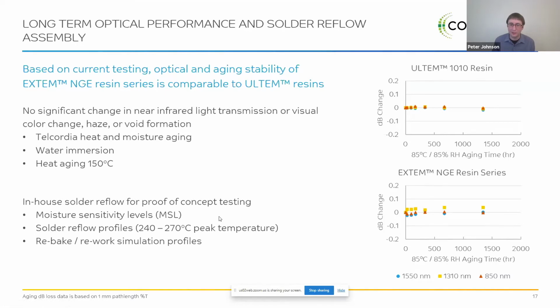of concept testing. So when we say we have done 3 passes at 260 degrees C, we've done it internally at various moisture sensitivity levels. The nice thing that we've learned about having our own machine is that we can vary the solder reflow profiles. We can make them short or long. We can ramp up the temperature. We can just let it sit and hold at 260 degrees C just to abuse it and make sure that there's really no failures going on.